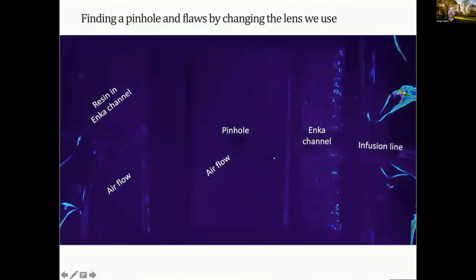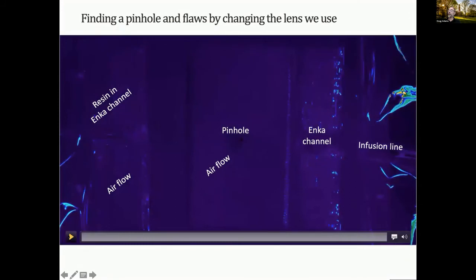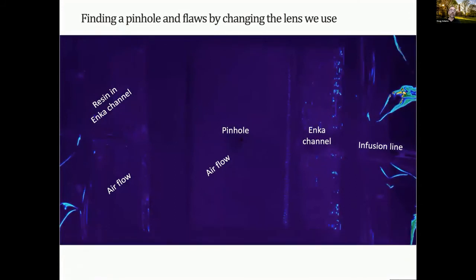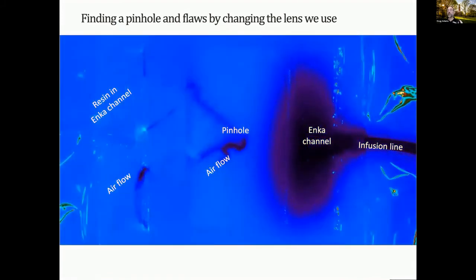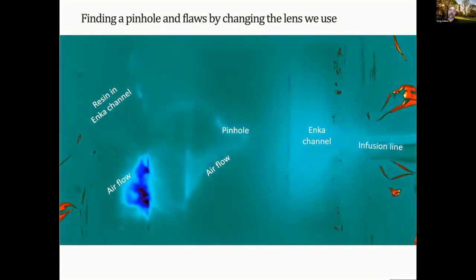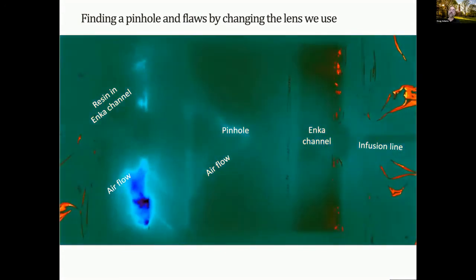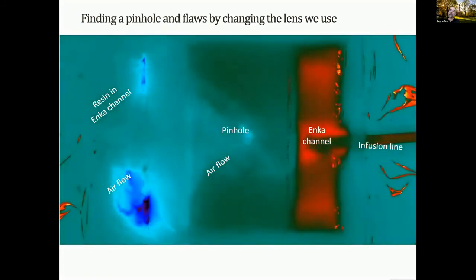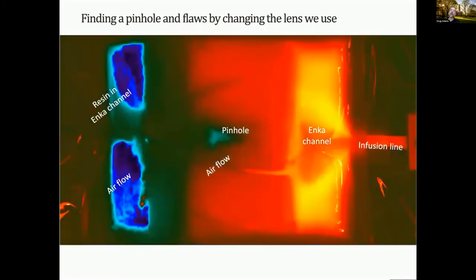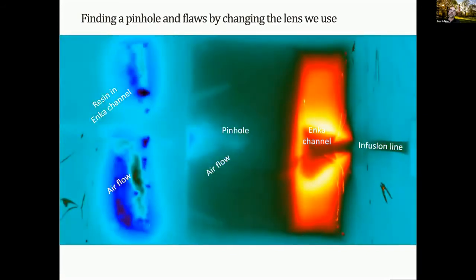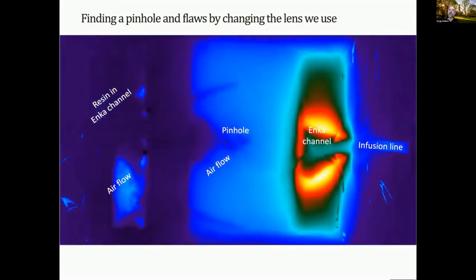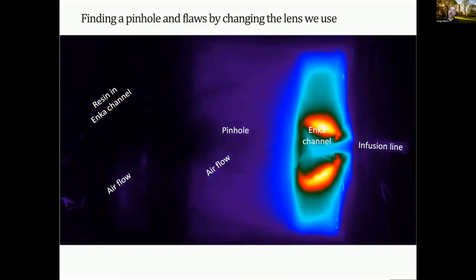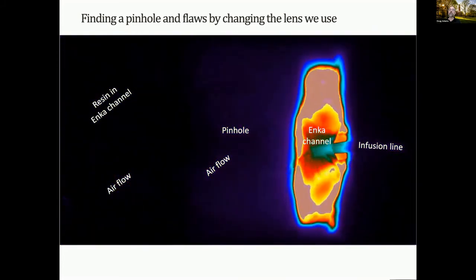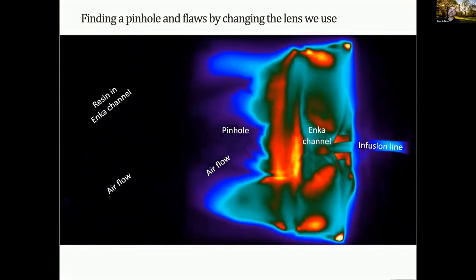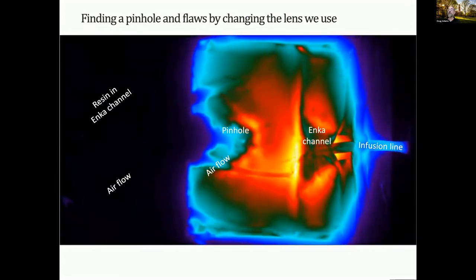For the most part, we saw part integrity, but on the surface, we saw some of this snowflaking. So if you're interested in what that looks like overall as the process unfolds, this is what you actually see. You'll see infusion. So initially, you see a temperature change because the resin is at a different temperature than everything else around it. And so you actually saw the infusion process. But then you'll start to see the curing process here, starting in the channel and then propagating across the part. You'll see kind of a heat wave move from right to left here in just a second. And so during these processes, there comes the wave. We're looking for anomalies in that heat signature.